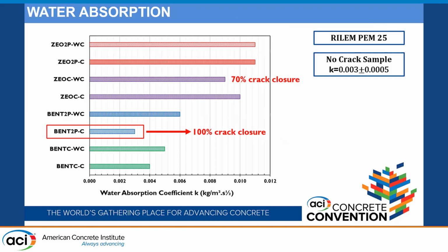When we look at the water absorption, the sealing ability was evaluated by determining the change in water absorption by applying the RILEM 25 procedure. Consistent with the crack closure image, bentonite shows a water absorption coefficient almost equal to the no-crack samples. But on the other hand, the zeolite sample cured in water, which had an efficient crack closure of 70%, did not show the same efficiency in water absorption. It can be related to the quality of the precipitation, which is vaterite, not as stable as calcite precipitation.